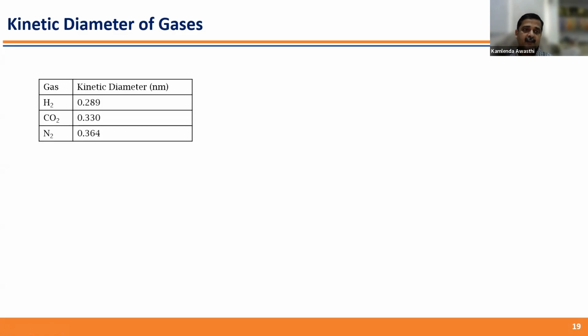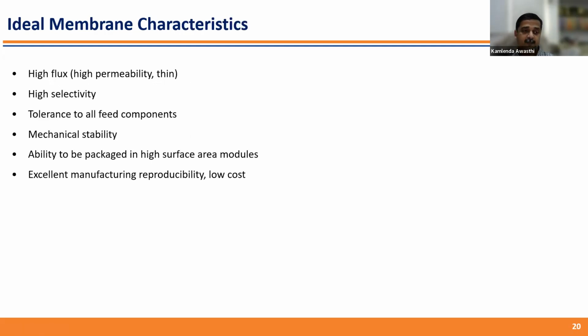So their kinetic diameters are very close to each other. We cannot make a filter of, say, 0.289 nanometers that lets only hydrogen through and blocks the rest, because everything we are discussing is in the nanometer range. If I say 50, 60, or 70 nanometers, every gas passes through comfortably. So how do we make a selective nanofilter to separate these gases? Certainly we can make polymer composite and other membranes.